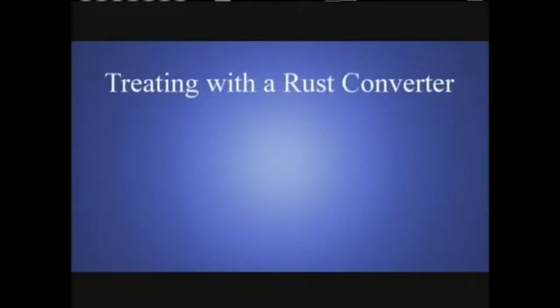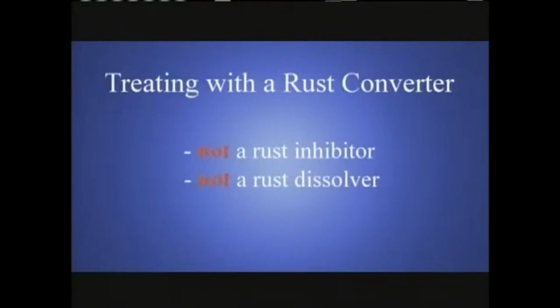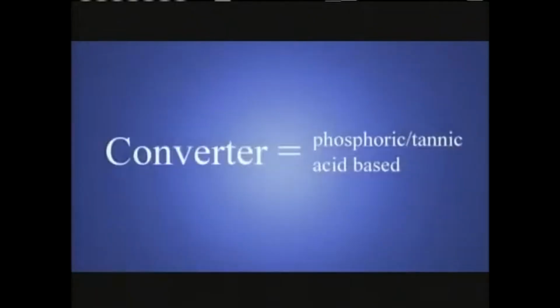Keep in mind this is a rust converter, not a rust inhibitor or rust dissolver, but a converter. A converter works by chemically changing the iron oxide into a more stable iron tannate or iron phosphate. Most commercially available rust converters are a phosphoric acid or tannic acid base. Some are even a combination of the two. The only word of warning if using a phosphoric acid-based converter